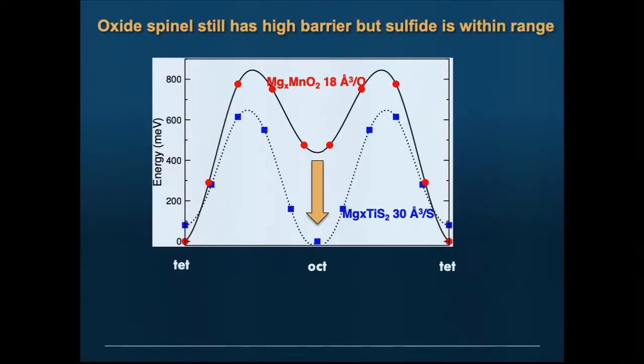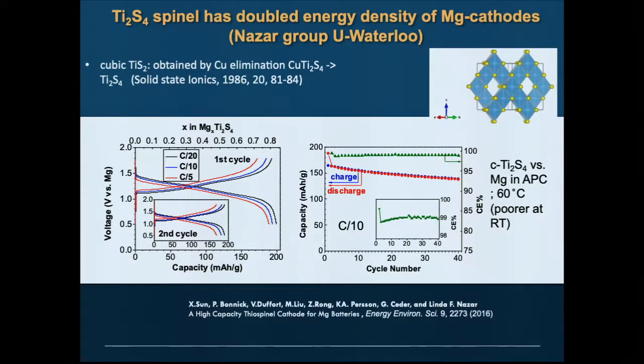Okay, so if you calculate that with an oxide, this is the migration path. It's still pretty high. It's about 800, 850 meV, which is still too high to do at room temperature. But if you get a little help from your friends, the anions, and you go to a sulfide spinel, because of screening, you can bring this down to 600 meV, which is not quite like lithium-ion, but that actually works. This is work we did with Linda Nazar as part of JCESR. If you take a titanium sulfide spinel, which you make by making a copper titanium sulfide one and leaching out the copper, you can actually cycle this at very high capacity.